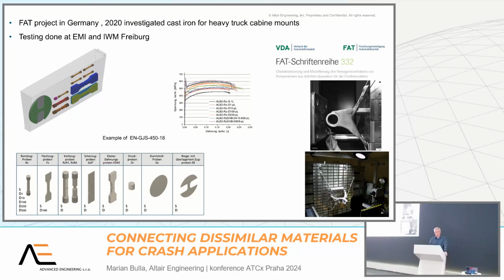And then we also did some material tests on quite dynamically loaded structures. For example, here, cast iron in this case, with different velocities and differently shaped test specimens for getting more information about the failure mode. So this tensile dog bone test is not sufficient anymore. We need more information on bulky materials, using the cylindrical tests for shear tests, plane strain, compression tests, biaxial tension test with this punch test, and so on. Sharp bending tests to determine and have more information about the fracture models.